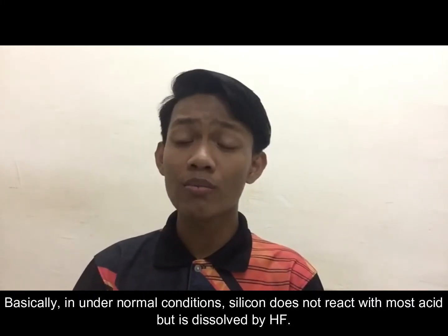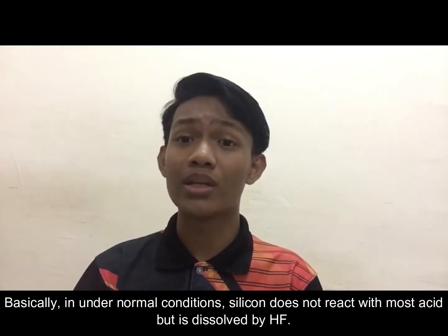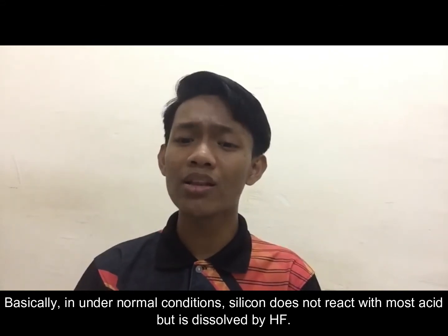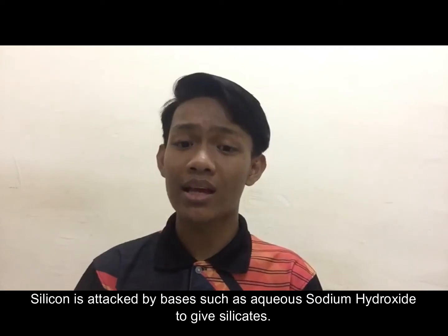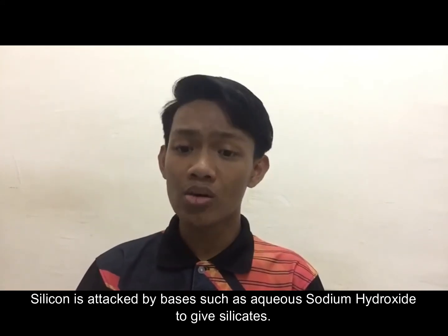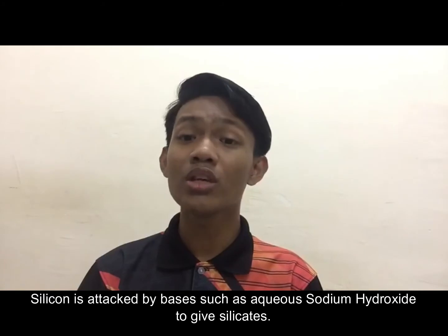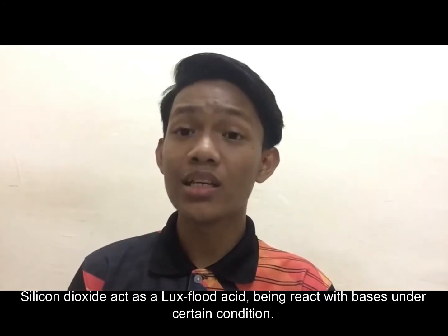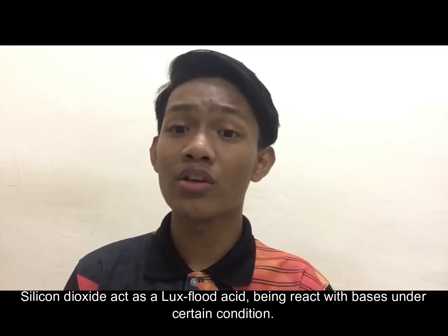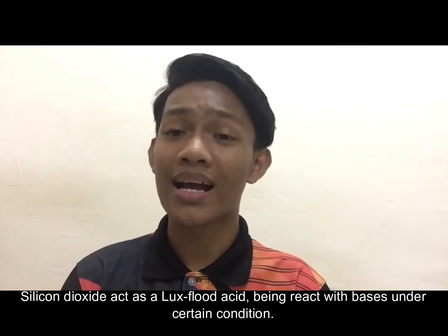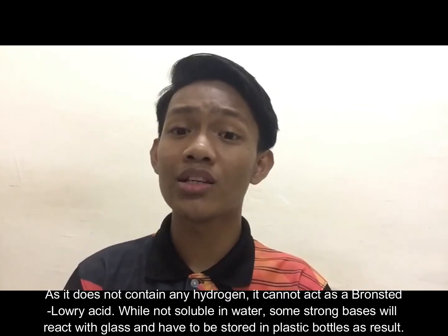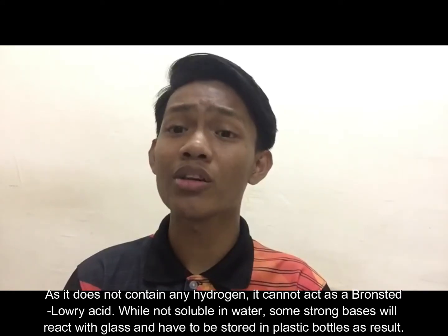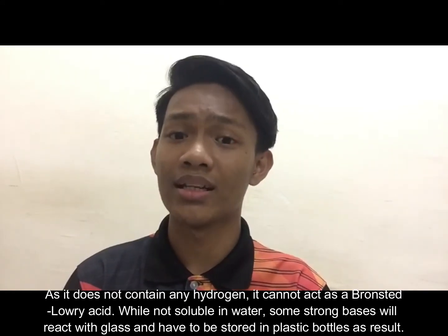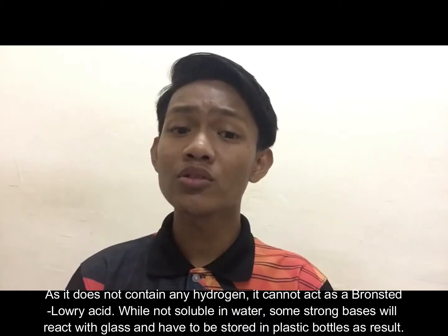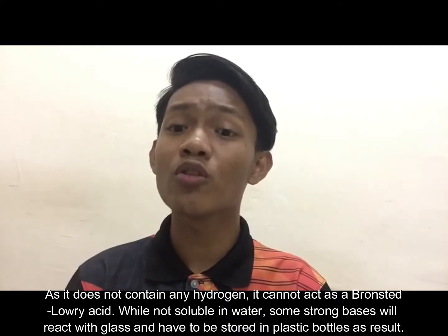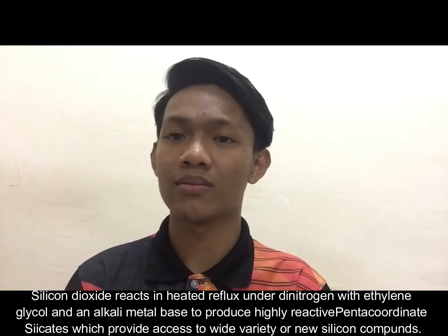Basically, under normal conditions, silicon does not react with most acids, but it is dissolved by hydrofluoric acid. Silicon is attacked by bases such as aqueous sodium hydroxide to give silicate. Silicon dioxide acts as a Lux-Flood acid, reacting with bases under certain conditions. As it does not contain any hydrogen, it cannot act as a Brønsted-Lowry acid. While not soluble in water, some strong bases will react with glass and have to be stored in plastic bottles as a result.